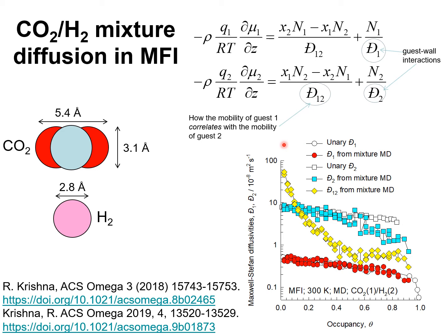We can use molecular dynamics to determine these diffusivities as explained in these publications, and the MD simulations for CO2-hydrogen mixtures are plotted against the pore occupancy in this diagram. The red circles represent the diffusivity D1 of CO2.